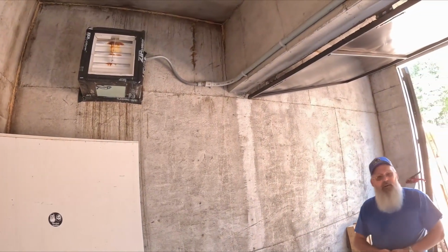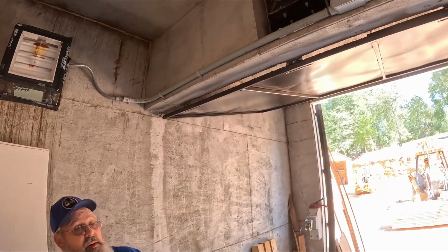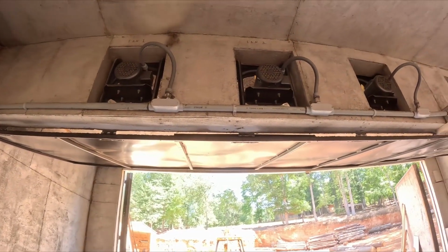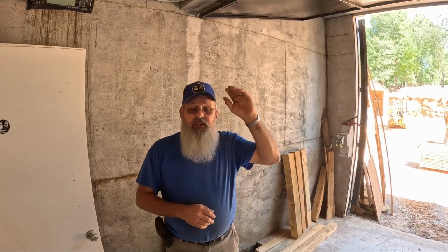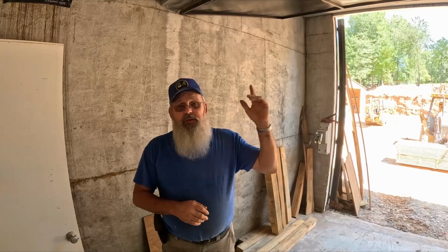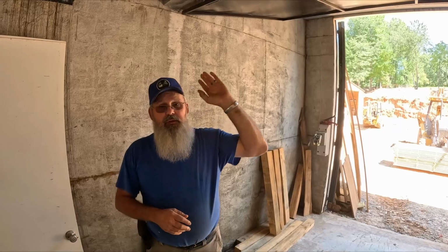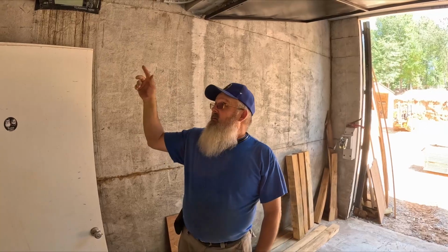Anything else in the box? The fans. I will tell you something about the fans. When we're doing pine, my goal is to get it to 120 degrees and 75 degrees on the wet bulb. As soon as you get above that 75 on the wet bulb, it starts pulling water out. Now, in the summertime, I do more controlling of the heat with these fans than I do with this vent. And reason being, I don't like that vent running when it's at 95 degrees and 75% humidity, because when it exhausts hot, humid air, it just sucks hot, humid back in.